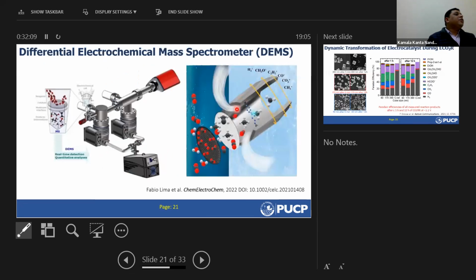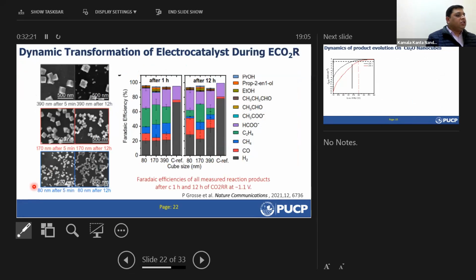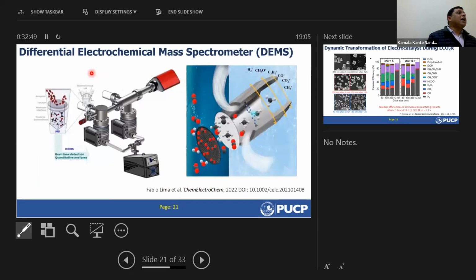Then, as I was saying, the catalyst surface is continuously evolving, it is dynamic, it is changing during the electrochemical reaction. And this is proven by the studies from Professor Cunha using an in situ liquid cell transmission electron microscopy during the electrochemical CO2 reaction. But they could not do the real-time product evolution and product selectivity measurement during the electrochemical CO2 reduction reaction on copper nanocubes, and they could not show the temporal evolution of product formation. So what we did is we adopted this technique, differential electrochemical mass spectroscopy.